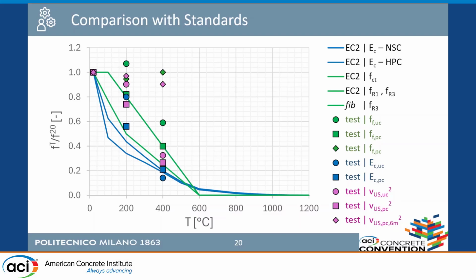Why did this happen? Because in this range of temperature, between 0 and 270, 300 degrees C, we have a strong effect of the thermal creep during heating. But in residual condition, we don't have thermal creep. So the effective stiffness that we can measure is far higher. You can see that the magenta symbols are quite consistent with the blue one, because they are trying to represent the same thing, because the second power of the ultrasonic velocity practically is the Young modulus. The only factor that allows to move from one to another one is the density, but the density of concrete, because of heating, changed just 10%, so it's not an impactful parameter.